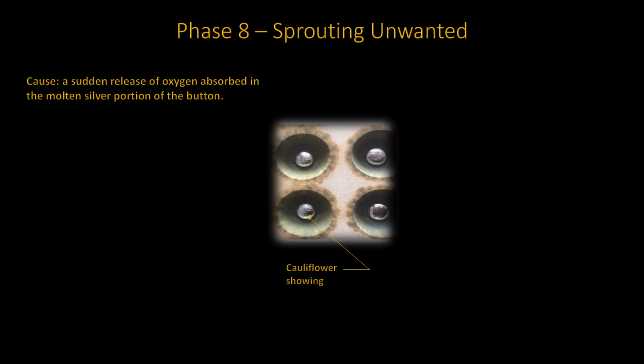However, if cooling was too rapid, a solidified crust may form too quickly. The center of the bead will still be molten. The expanding oxygen will erupt through the crusty surface, similar to the gases erupting from a volcano. The material will be dislodged, splattering precious metal out of the bead, resulting in the loss.